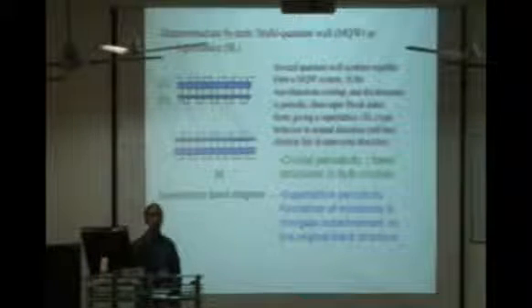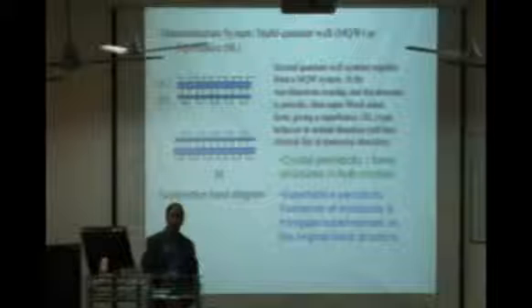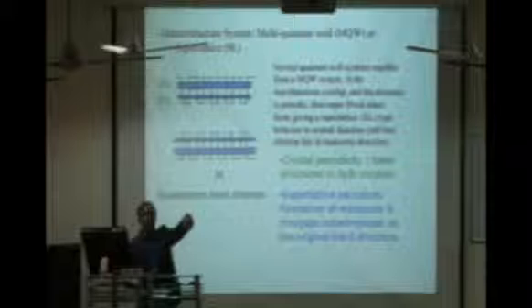In this case, the periodicity of this growth of the material, that means what is the thickness of the well and what is the thickness of the barrier, gives some kind of periodicity, what is known as the superlattice periodicity. But actually what is important is that you get something like this. So earlier you had only conduction band and valence band. Now inside the conduction band, you get formation of subbands or formation of mini-bands. As you see, in the conduction band now you have one mini-band here and one mini-band here. So there can be now electronic transport between these mini-bands.